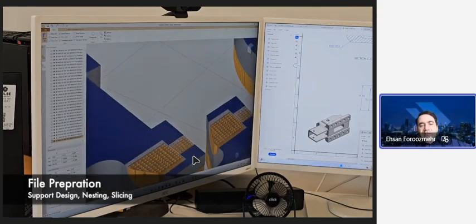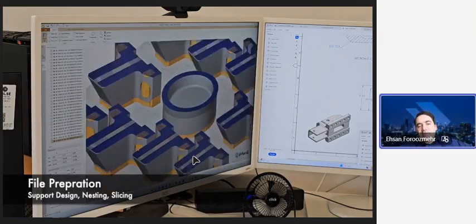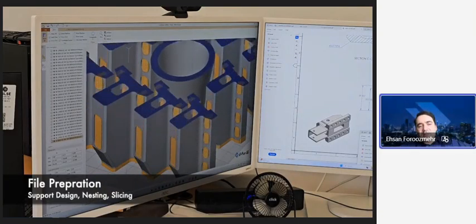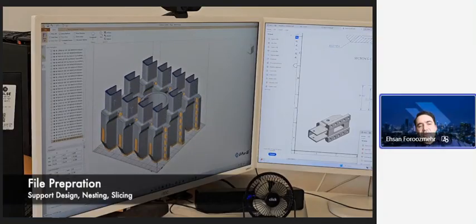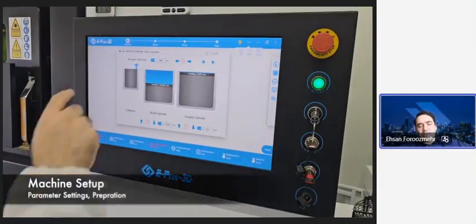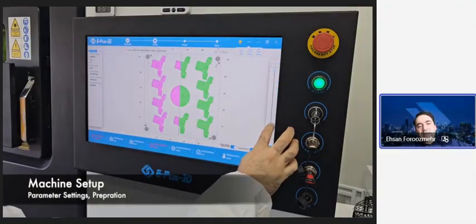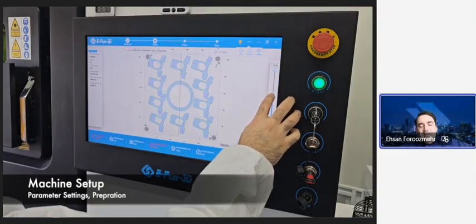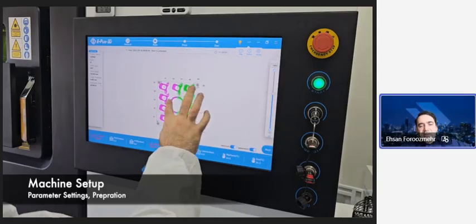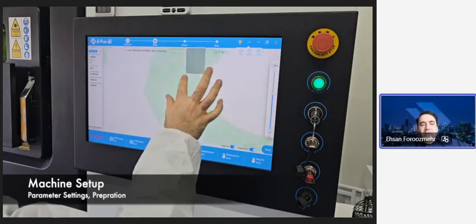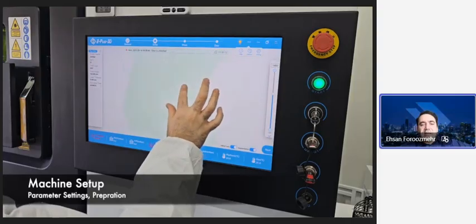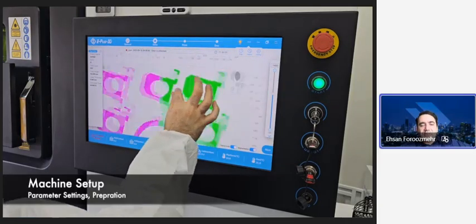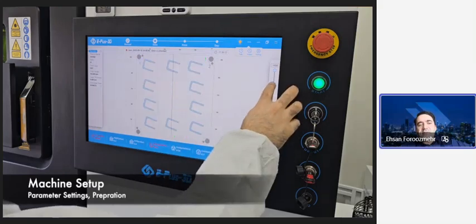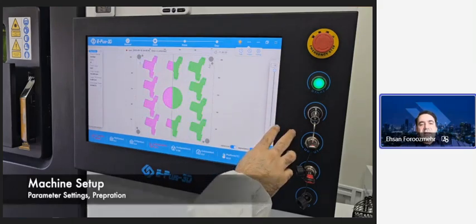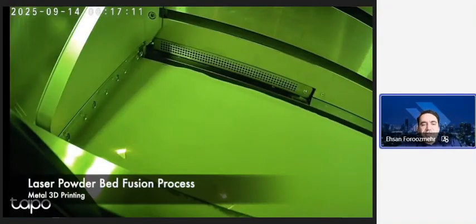And we slice the parts based on the layer thickness that is critical for us. The layer thickness, we talk about tens of microns. So it is about 30 micron, 40 to maybe 100 micron, or even more. These are the layers that you can actually see, and all the parameters, including the laser movements, are the tracks that you can actually see in this movement. So everything is predefined in the software and then transferred into the machine.